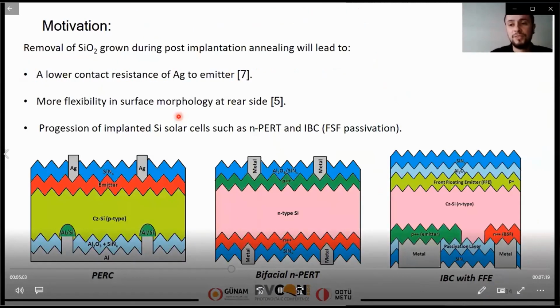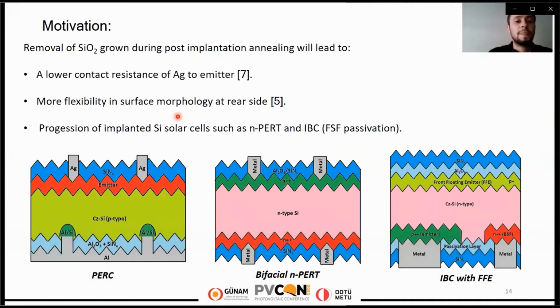So what is our motivation in this study? We would like to eliminate oxygen flow during the dopant activation to prevent silicon dioxide growing at the front and rear side. Because when we do not have silicon dioxide at the front side, the contact resistance of silver to emitter will be low. Also, since silicon dioxide limits the morphology choice at the rear side, we will be more flexible in terms of rear side processing in the absence of silicon dioxide at the rear side.